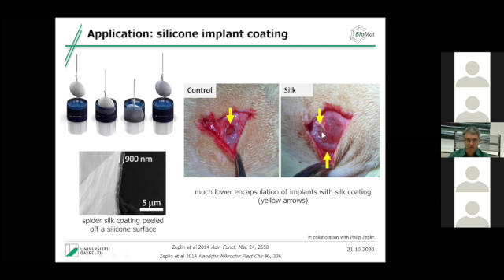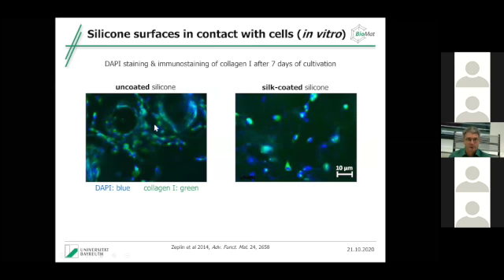In contrast, if you look at the silk-coated implant, you see there's no capsule. There's actually just tissue growing around. You even see vascularization, and this makes this coating very, very successful. Here you see what happens with the cells. We just had some DAPI staining, which stains the cell nucleus, and some collagen 1 staining after 7 days of cultivation. With uncoated silicone, you see that the fibroblasts grow and have a lot of collagen production. With the silk-coated silicone, as before, they're not even spreading out, they're not proliferating, they're not making collagen. And this is the explanation why we don't get capsule formation and we don't get fibrosis.